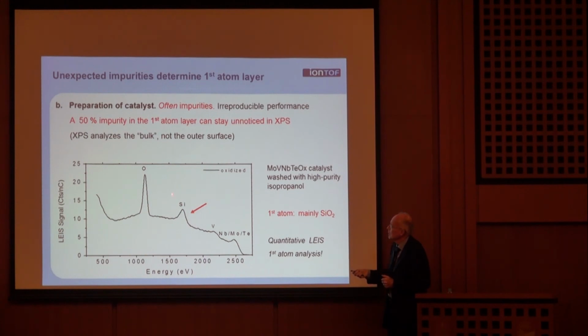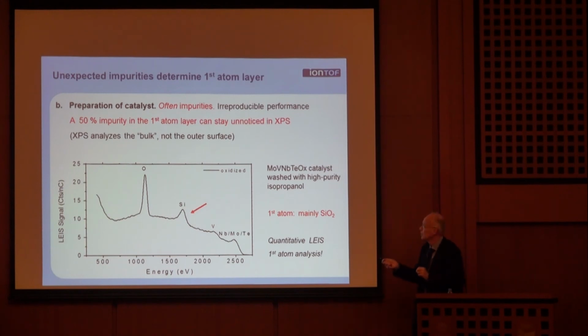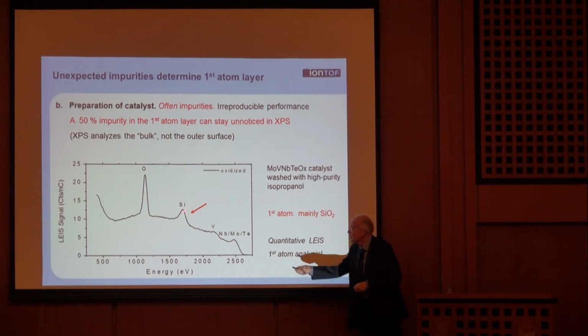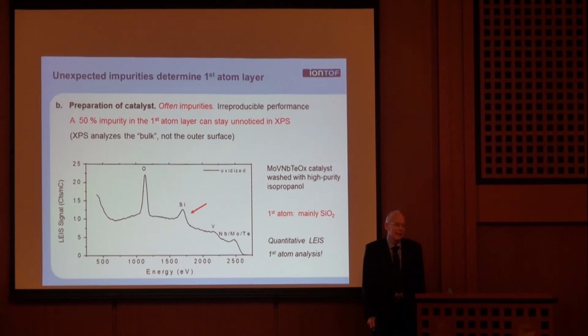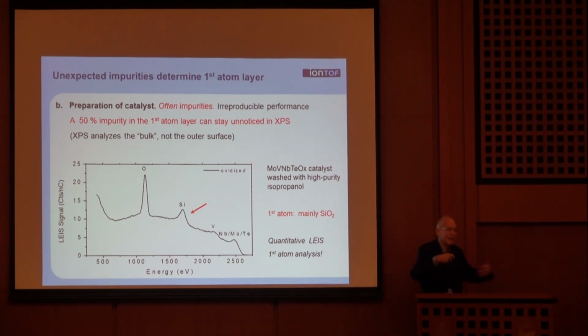And we looked at that catalyst and, well, silicon should not be there. You see a lot of elements, but not silicon. You don't see much of the other elements. What happens? The isopropanol was the highest purity isopropanol you can buy, but it contains impurities. And so, when you do that, there's a little bit of siloxane in there, 10 ppm in the solution, and all the siloxane gets to these molecules. So, in fact, the surface is at the end mainly silica. And so your catalyst will behave very differently because of that.